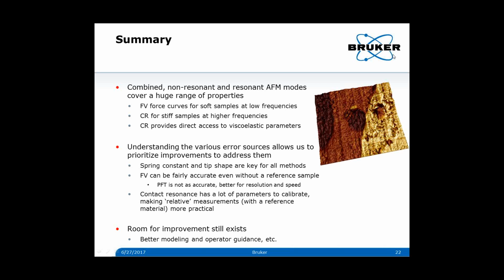Very good. And I think I'm going to go back to Dalia on this one, and you can certainly chime in, Bede, but high frequency can damage the tip very quickly. Will not that be a waste of tips in your experiments? You know, the high frequency combined with the load that you're using. So both in, I don't know if they meant for contact resonance or peak force, but certainly in both of those, you are controlling how hard you're pushing onto the sample. And again, it's going to depend on the sample.